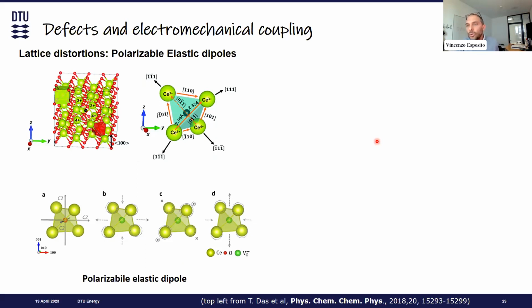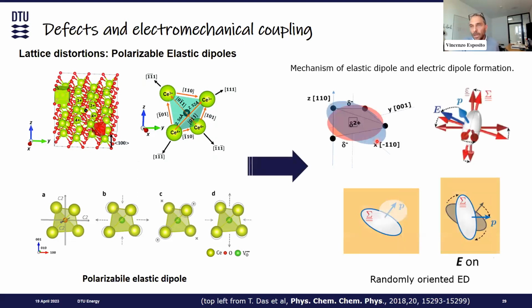This is basically a distortion, a local distortion in the solid solution, and easy polarizability of the material. So when we apply an electric field, the charges around the defect can change direction and drag around the elastic dipole. We don't have time to go through this. I'm open to answering questions about this topic, but this is more or less the dominant model that we have in mind right now.